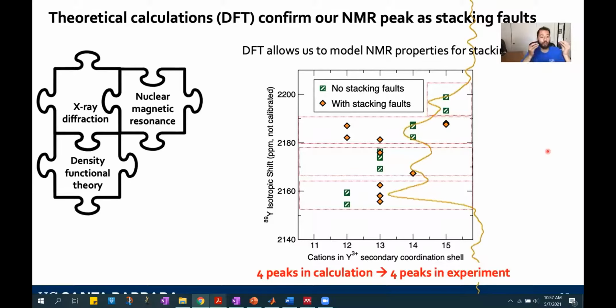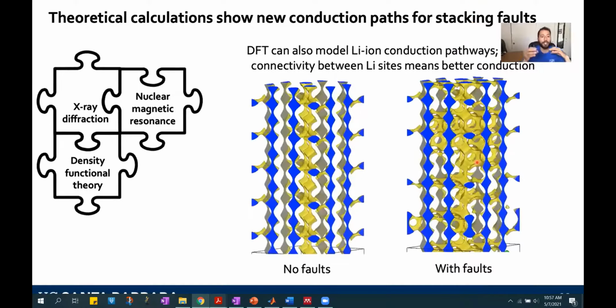When I have stacking faults, though, I can see that this perfect little bin representation breaks down, and that's corroborated by that 1 broad peak that we observed. Now I want to understand the conduction properties of this. So I can start to use density functional theory to model lithium ion conduction and transport pathways through my material.